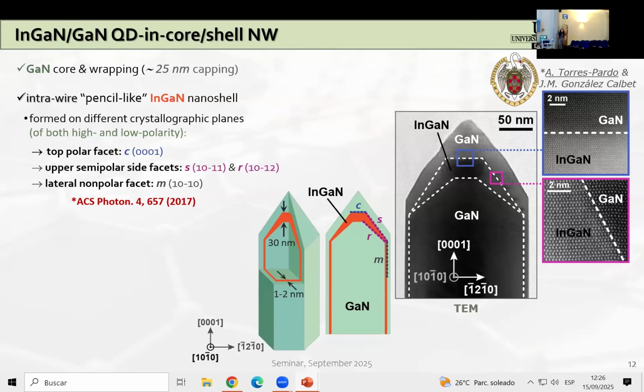transparency. So the actual structure of our nanowires is a core-shell, which means that there is a very thin indium gallium nitride layer embedded inside of this gallium nitride nanowire. And as we could see in transmission electron microscopy images recorded on individual nanowires, this intrawire InGaN nanoshell is formed on different crystallographic planes of both high and low polarity. So this includes the top polar facet, then we have the upper semipolar side facets, and finally, we have the lateral non-polar facets.